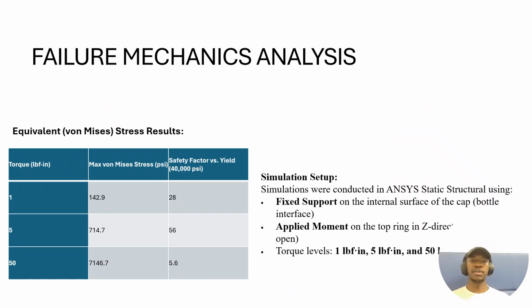So for failure mechanics, I made 3 simulations, and they were run at 1, 5, and 50 pound force inches. And this allowed me to analyze cap performance under light, moderate, and excessive torque levels. I wanted to see what happens when I apply light torque, some moderate torque, or some excessive torque levels. And to me, light torque is about 1 pound force inch, and when you apply that, you get a max stress of 140 psi, which gives you a safety factor of about 28.